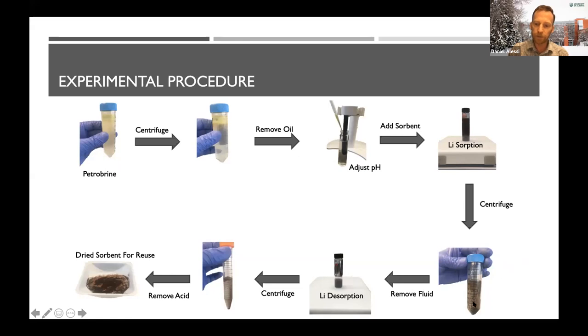All the lithium that was in this large volume is now concentrated into this little bit of powder. You can see we put that into a vial again. We add just a little bit of acid so that when the lithium desorbs, we go from the 40 ppm lithium up to over 1,000 parts per million lithium. We centrifuge again to recover the lithium-voided sorbent, because we want to dry it and kick it back into the cycle and reuse it 100 times. What we have here is a far smaller volume in which lithium is concentrated. That's the stuff we would send off for post-processing. We would clean it up to remove other impurities that didn't quite make it past the sorbent, and ultimately we would produce the battery grade salts from that.